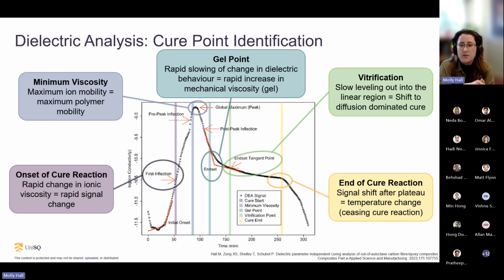The vitrification point, which for this I've defined as the crossover of your Tg and your temperature, which aligns to that shift to diffusion dominated cure, aligned very well to the tangent point after that end set. So where that signal really starts to level out. So if you notice on this, the signal doesn't get perfectly flat. And this definition is how I've defined vitrification for this. There are several other correlations that have used definitions like when the signal levels out, when the derivative reaches 0, when it plateaus, and these definitions didn't really work for how my signal was showing.